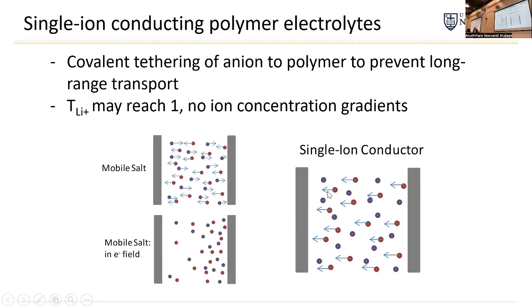In a single ion conductor, only one of the species is able to move. Because electroneutrality must be attained, this ion concentration gradient does not form, and you get more uniform ion distribution. When talking about polymers specifically, the way that we achieve this is by covalently tethering one of the ions to the polymer backbone. And then the polymer is not able to move long range, so that ion isn't able to move either. So if we're talking about a lithium ion conductor or a sodium ion conductor, you would covalently bond the negative charge to the polymer, and then only the cation would be able to move. Of course, in these systems, the cation transference number can then reach unity. It's not unity though if the polymer is in a dilute solution and is able to diffuse and move.